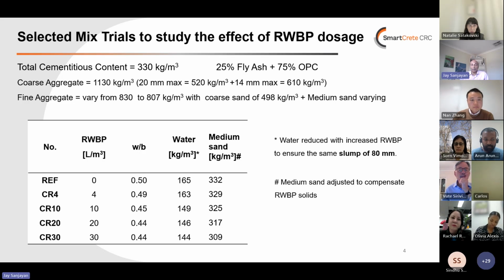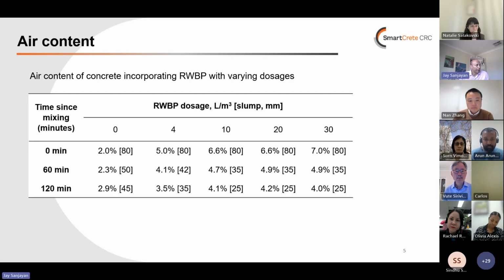But at the same time, the water, we reduce it to balance the slump. So when we add the paint into the concrete, the workability goes up, so we can pull off some water to compensate, to maintain the slump. So the water binder ratio effectively decreases.